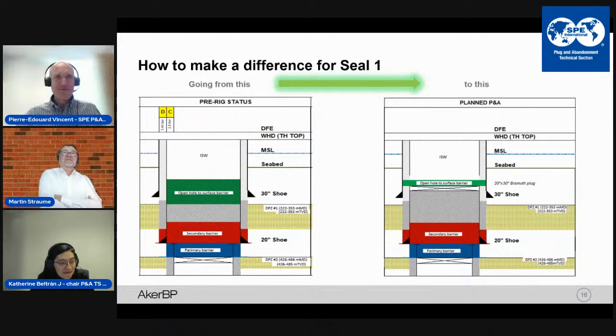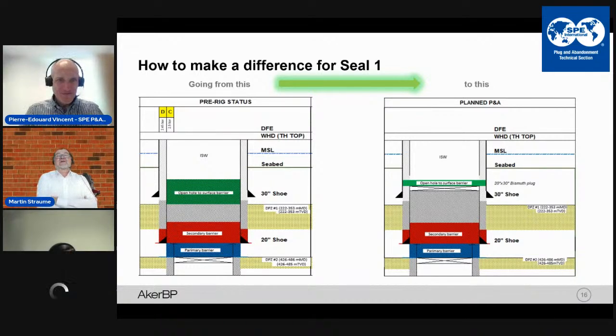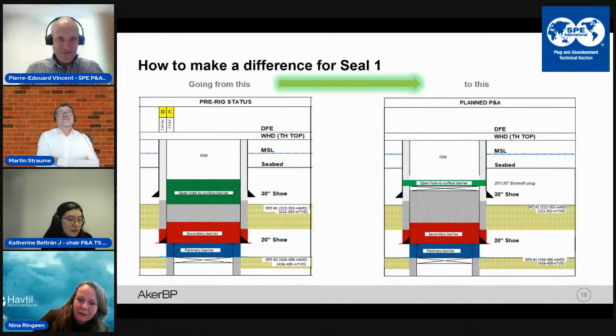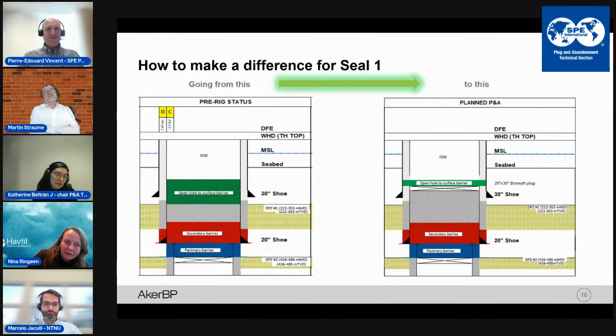That's the issue, it depends a little bit on where the leak is. If the leak is out towards the outer casing, it's really hard to discover on a log. If the leak is between the inner casing and the cement, that's where the log is intended to show you the bond. So even though you get a good log, unfortunately, it's possible that it could leak like you saw.